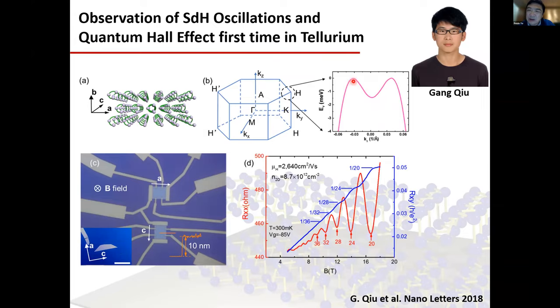But without high pressure, the valence band is like this. People did some theoretical work there, and also spin-resolved ARPES. So spin is different, let's say, for minus K and positive K. But it's not the Weyl point, it's not the crossing, and it's different at the H6. So this is H4, the next one is called H5, then the next one is H6, then the crossing point, then the Weyl point. So the conducting band is the H6. These are known, okay?